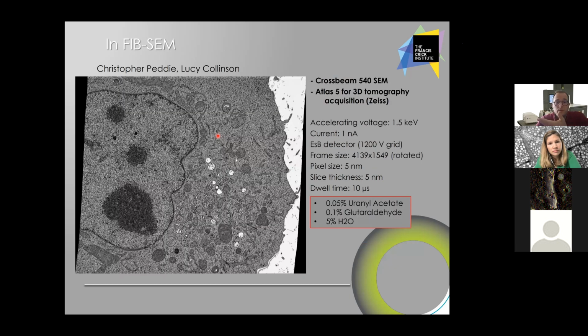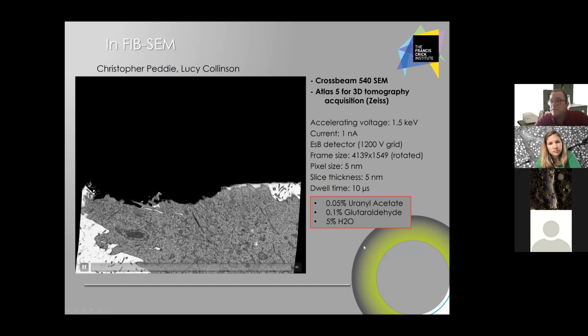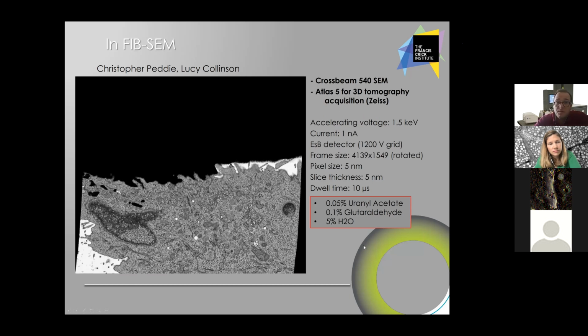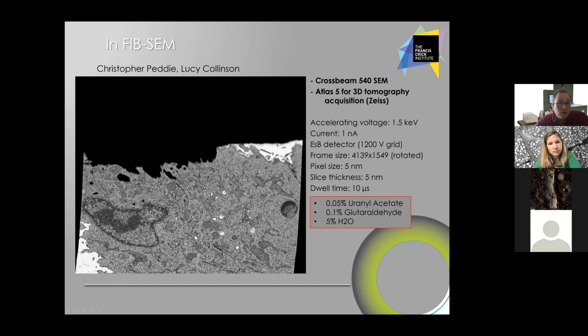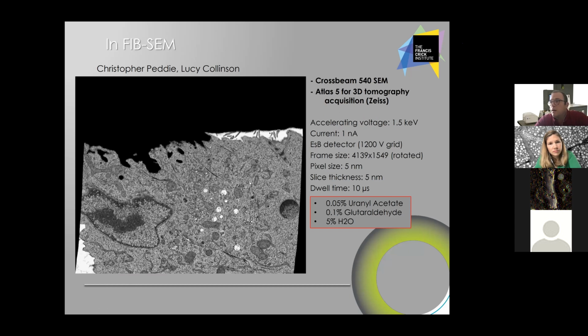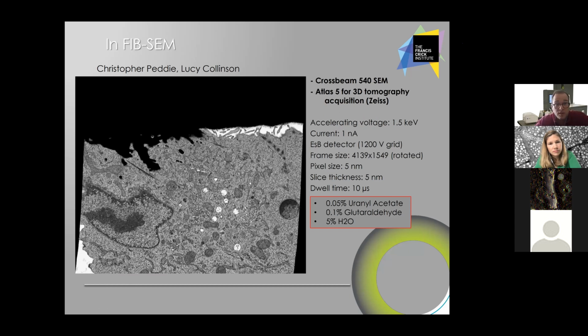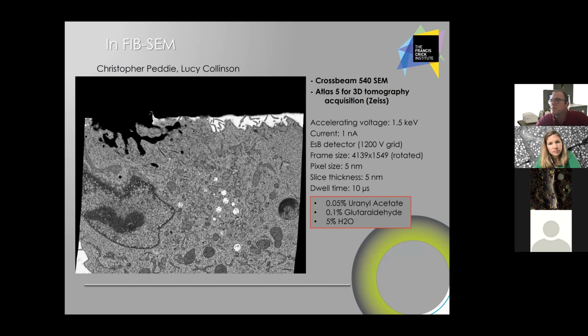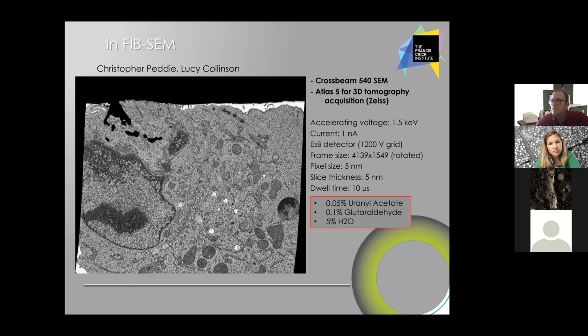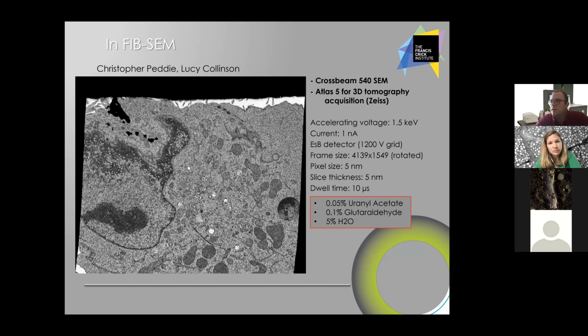The same sample, or the same block, was also put into the FIB-SEM microscope, and again, we had some very high contrast. So I know that the FIB-SEM is giving much higher contrast natively, and this is confirmed here. There's nothing novel in this case, but this gives to us very encouraging results.